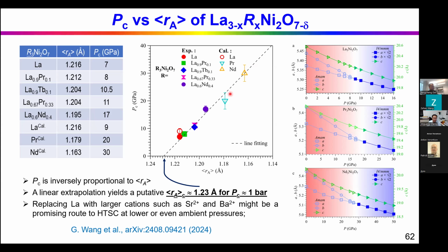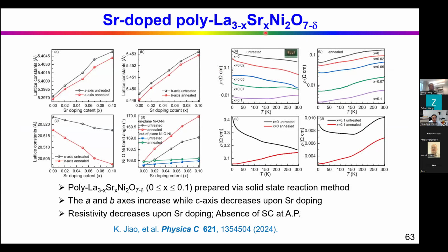And from a linear extrapolation, we can get a critical size for the A-site cation at about 1.23 angstrom. So actually, we need larger A-site cations in order to reduce the PC to ambient pressure. So not replacing lanthanum with smaller cations, but with larger cations, such as strontium and barium. Maybe it's possible, but so far there are some reports about the strontium doped samples.